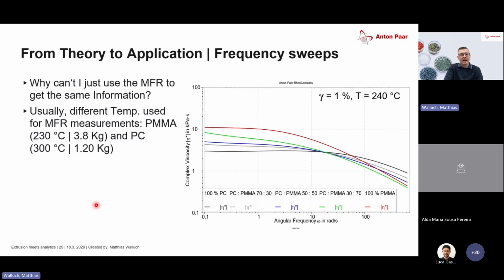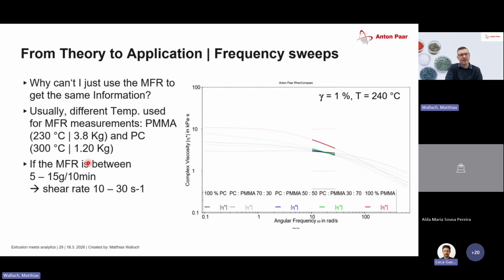However, we see that the MFR for these materials is 5 to 15 grams per 10 minutes, which correlates to a shear rate of 10 to 30, which is exactly this point. So from the MFR value, we would get the same value four times: for PC, 70% PC, 50% PC. Only the neat PMMA will show a different, lower MFI value. So this means we don't have any information about this behavior and this behavior over there, which is in principle important for my process because the material will behave completely different in process conditions.